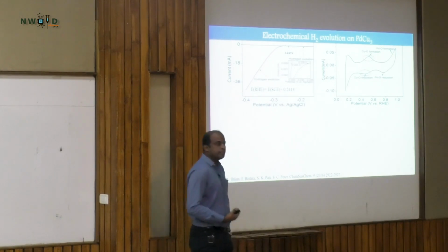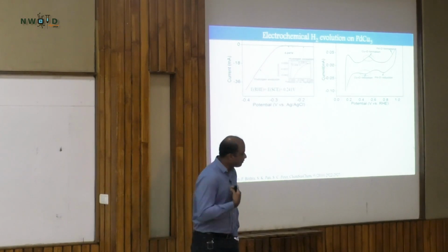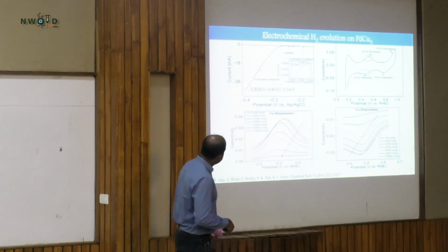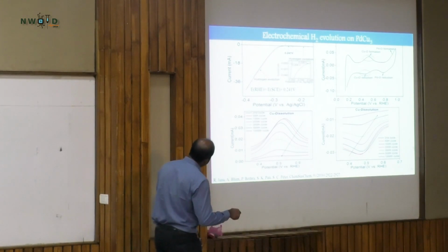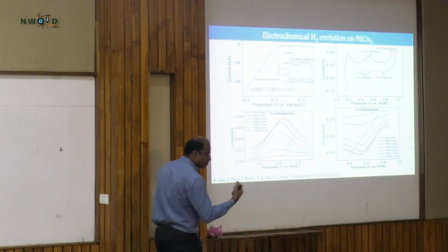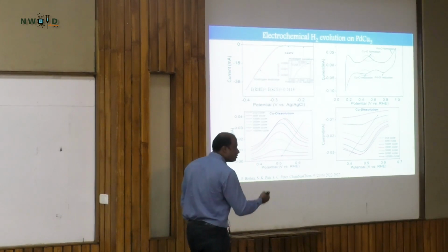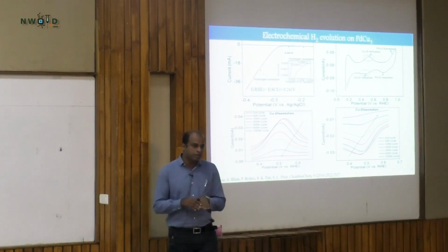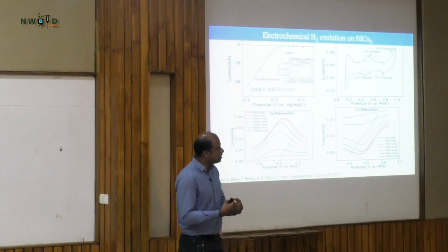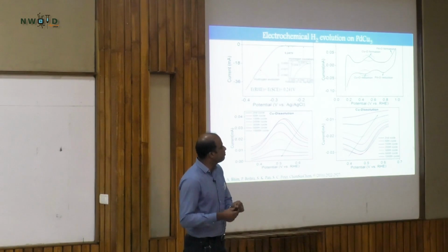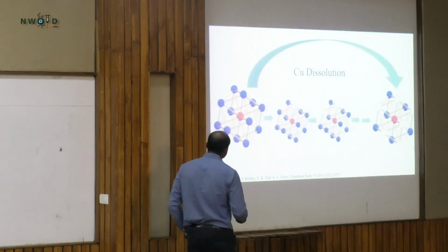And this is actually nothing but copper slowly etching out from the system. We continue this one. The copper oxide formation peak slowly goes down. The copper steps are coming off. And same as here, the copper oxide reduction peak also goes. So that means from the palladium copper system, copper is slowly etching out. It is generating a palladium copper 3 minus X system.